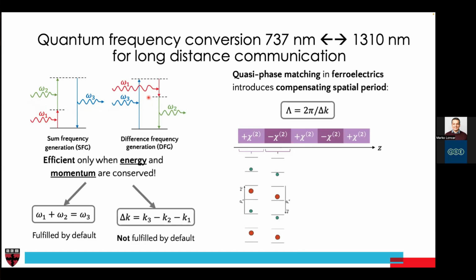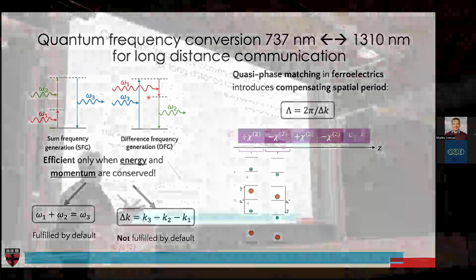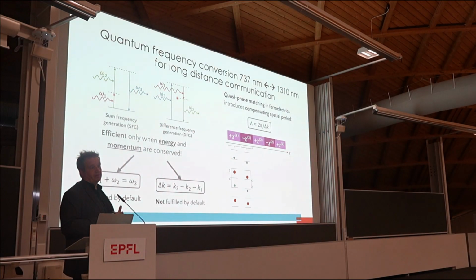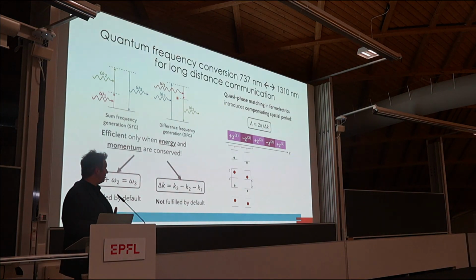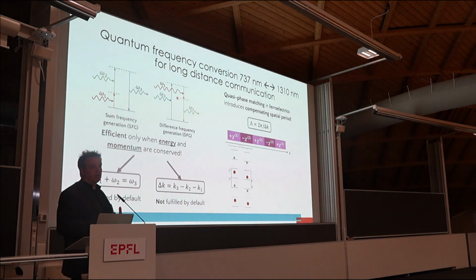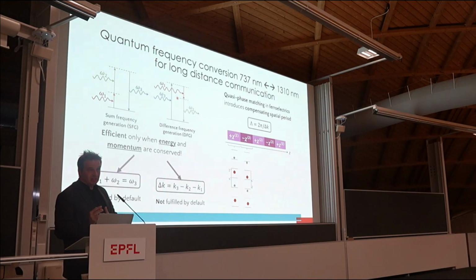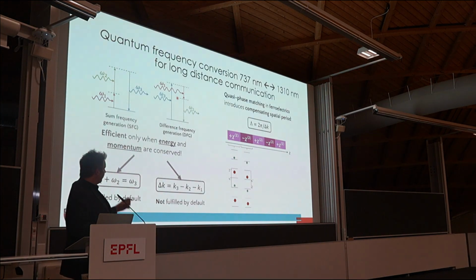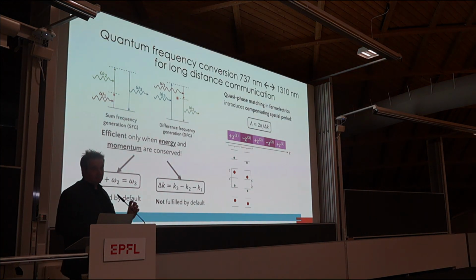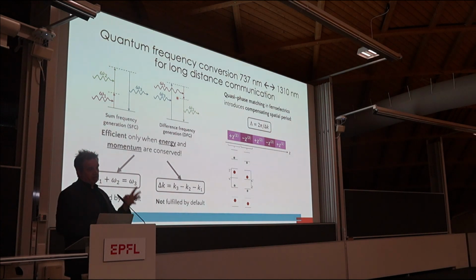and importantly deterministic. A lot of papers in this field, I really like the first presentation, and also what Camila is doing here: you pole lithium niobate, you measure some conversion, great. And this conversion, due to material limitations, typically is about 100 nanometers off from where you want it to work. Okay, maybe it's efficient, but it's not where you need it. We have about 10 gigahertz room for error, because we need to go 737 plus or minus 10 gigahertz to 1310 plus or minus 10 gigahertz. That's it.